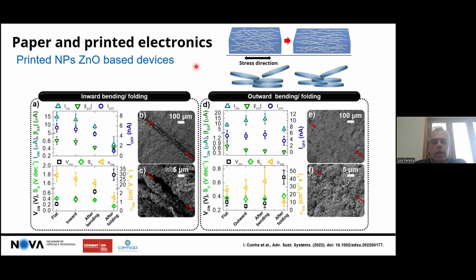And indeed, this strain, what we observe is that in some cases it could be beneficial, because if you put a tensile strain, you may force a better alignment and assembly of these nanoplates. And you see here now the benefits comparing the inward to the outward. So when you put a compressive stress on these particles or when you put a tensile stress on these particles, you see that the films, in this case here, resist much better when they are made of nanoplates to the outward bending.